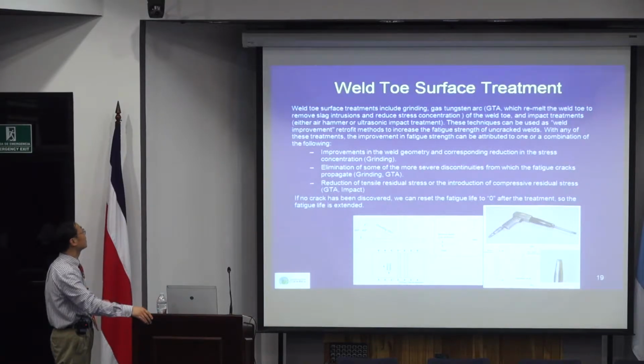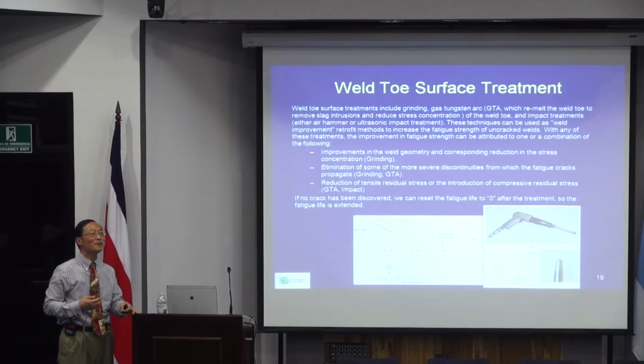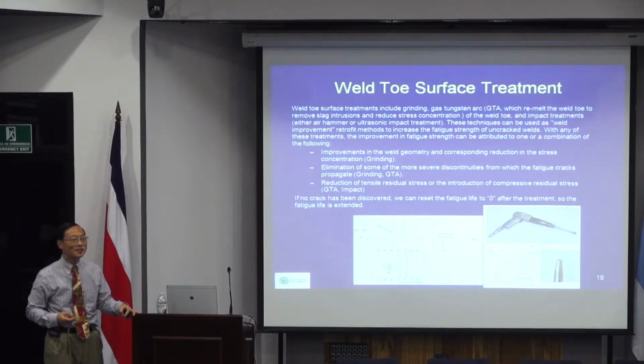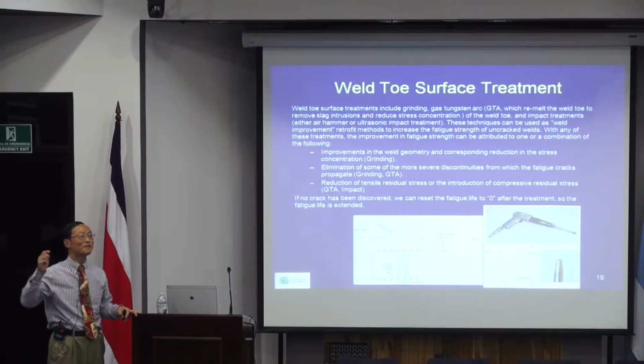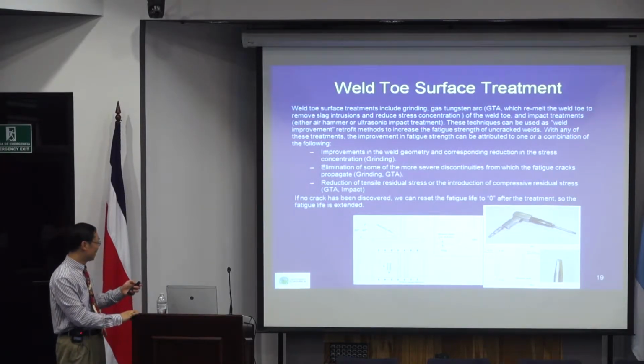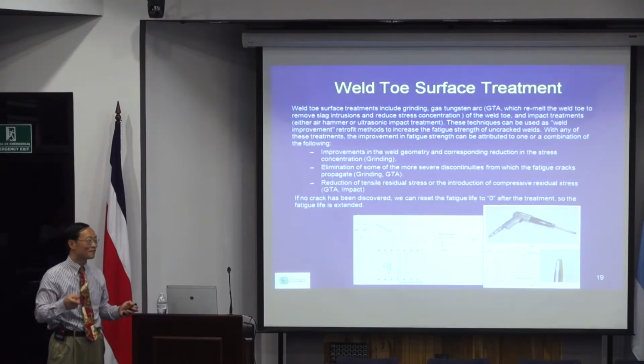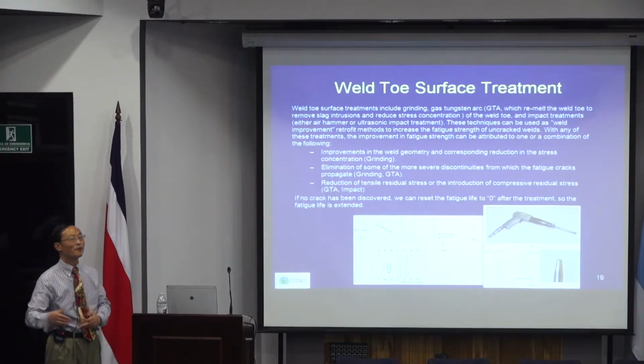And which means the stress... another thing: if you have a relatively new bridge, and the designer forgot about the fatigue check, and then later somebody says, well, the bridge should have 75 years of fatigue life, and you forgot to design for that, and now you have only 60 years of fatigue life. What can you do? Research has found that because fatigue is the accumulation of energy, if you use a small hammer, almost like a massage, on these crack areas, actually you can reset. Like if the bridge is already 5 years old, you do that once, and you can reset to the original state so that you can prolong life for another 5 years.